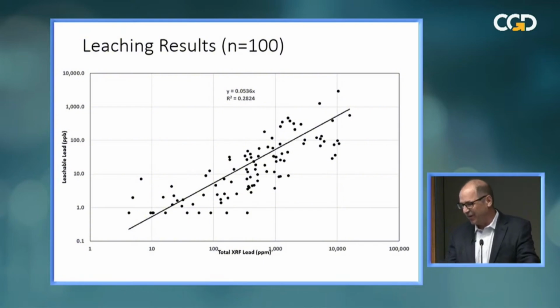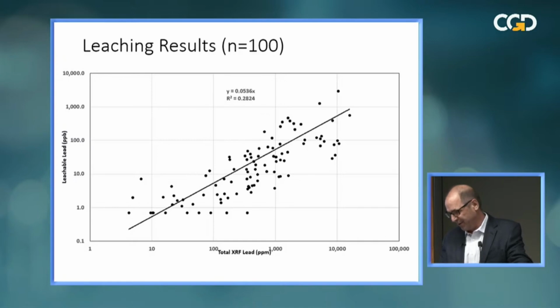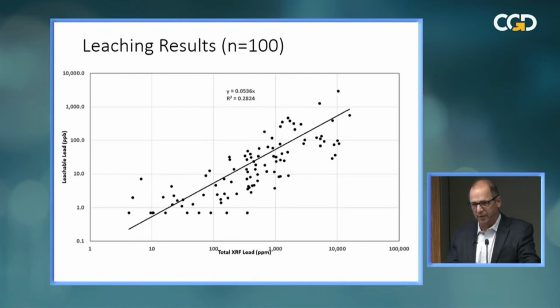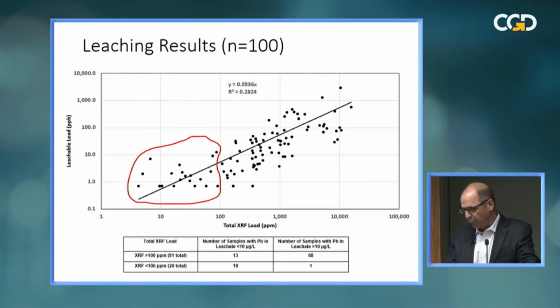And you can see the R value, the correlation coefficient, of less than 0.3, which is embarrassing, right? Now, would you expect anything better? I'll tell you no. But just to put things in perspective, for a pot with a total lead of 1,000, you could get anything from leachable lead from a few parts per million to a few hundred parts per million. That's not a great correlation, right? And we'll talk more about why.